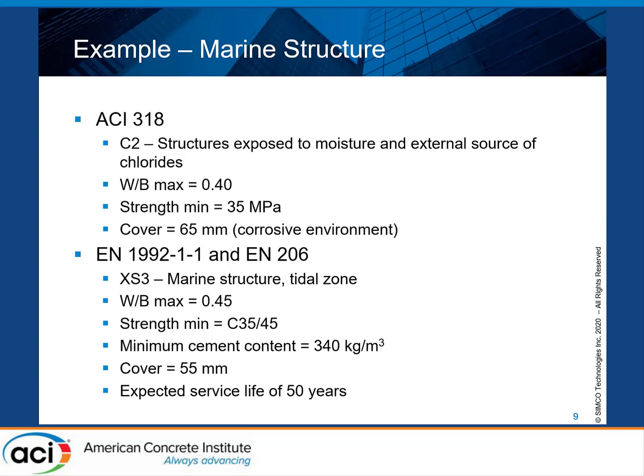I used also the European code. So based on these requirements, it would be an XS3 for a marine structure. And then I decided to use the tidal zone, because in the European code, the tidal zone is considered as a more severe exposure than the splash zone, than the submerged zone, sorry. So submerged is XS2 and tidal zone is XS3. So I decided to use the worst.